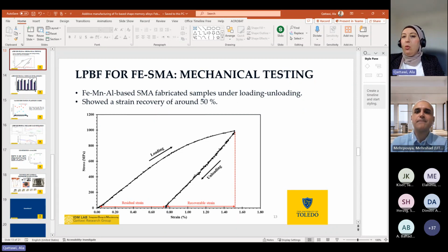Yeah. So we're still working on that. This is actually a very fresh result we got. Now there's a new technique we're going to apply for these specific samples, where we have a micro indentation that correlates to the stress-strain diagram. So it actually measures the microstructure and not only a dog bone style tensile test sample. So hopefully we'll follow up with more results on the stress-strain for these specific samples.